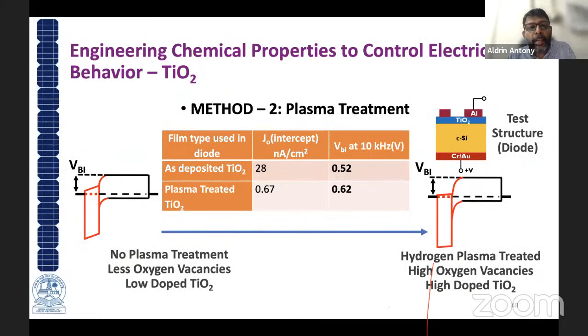So then we introduced a novel method to increase further the oxygen vacancies. We subjected this film, the atomic layer deposited titanium dioxide, to a hydrogen plasma treatment, as a low temperature treatment, that's a room temperature plasma treatment method. When you are exposing this material to a plasma treatment, a hydrogen reduction reaction will take place, which increases a lot of oxygen vacancies in the sample, which results in pushing the band down or the Fermi level up. The Fermi level goes up because of the conductivity increase, due to the vacancy increase of oxygen. And that in turn helps to increase the built-in potential.